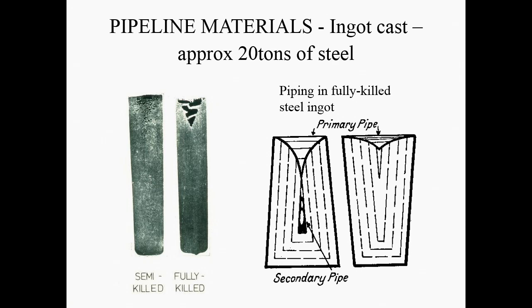The fully killed steel, which is the one where all the oxygen comes out, we get this crater at the top, which you have to cut off. But this material was relatively free of bubbles and free of oxygen contamination. And an ingot is typically cast with approximately 20 tons of molten steel from a blast furnace, so it's a lot of material. And it's cast into a mould, and the mould is this sort of shape here. And you can see that it solidifies on the mould wall, which is cold, and then it solidifies here, and then here, and then here.